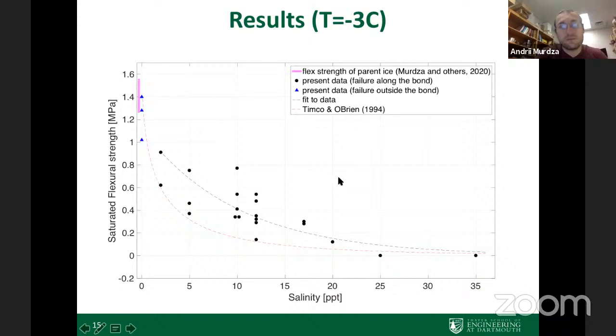So here I want to show the results for the flexural strengths, and I want to emphasize that we're now investigating saturated flexural strengths. So we look for the strengths after something like 15 hours or more, usually around 24 hours, as a function of salinity. So we did use different salinity sprays to make the bond.